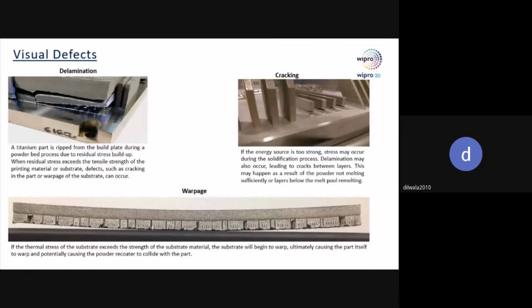If it lifts up from the build plate, it is delamination. See, our build plate is here. Lift off didn't happen here. It is happening somewhere around here. So this is cracking. If it happens here, it is delamination. You see here, right? It is happening at the intersection of our actual part with the build plate. So this is delamination. Here it is not happening. It is happening on the part after a certain number of layers during solidification. So this is cracking. This is the difference between delamination and cracking.